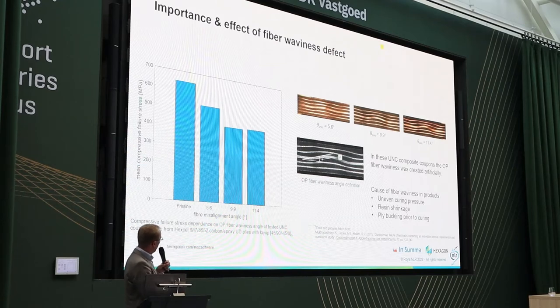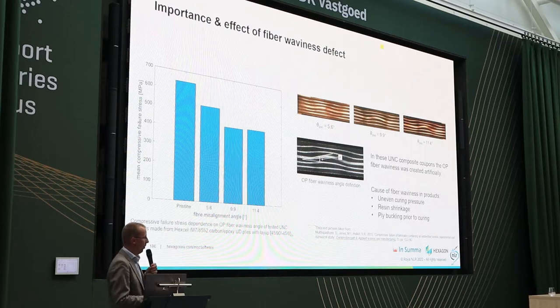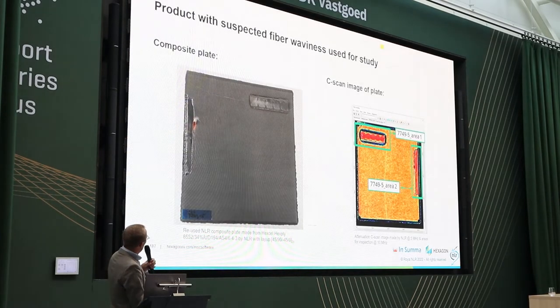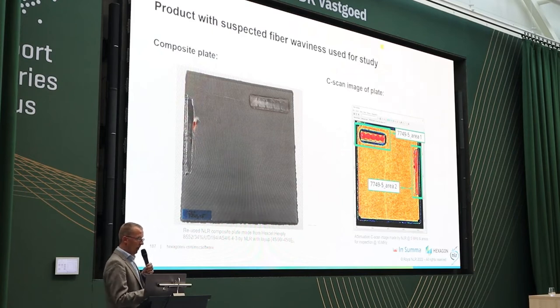These coupons were intentionally made with artificially created fiber waviness, but in a product for an aircraft it can be caused, for example, by uneven curing pressure, or resin shrinkage, or ply buckling. So those can be the causes. For this study, I went looking inside NLR: do we have products with fiber waviness that I can use, or should I make a plate with waviness artificially?